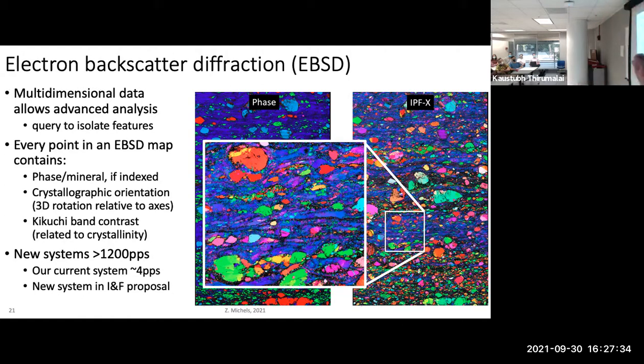So you actually have at every single point a wealth of information about that single point. Its phase, its band contrast, which tells you about its sort of crystallinity, its orientation. And so we can make different images from that sort of multi-dimensional data set. It also becomes easier to query parts of your microstructure that are otherwise difficult to do from an optical image, where you have to maybe tediously trace things or take a bunch of differently polarized images. And so it's very powerful.